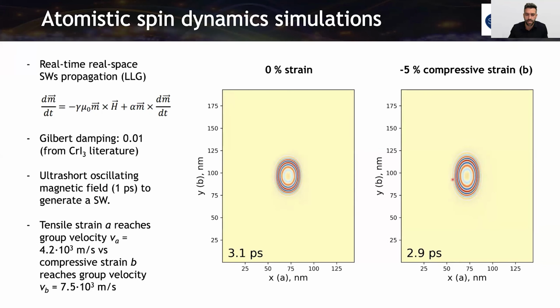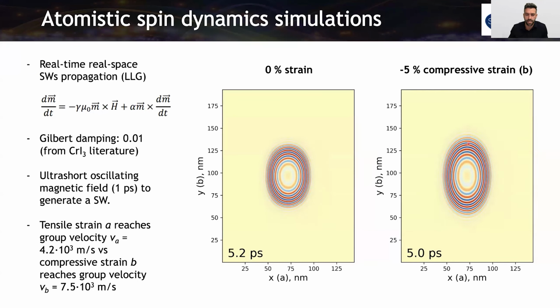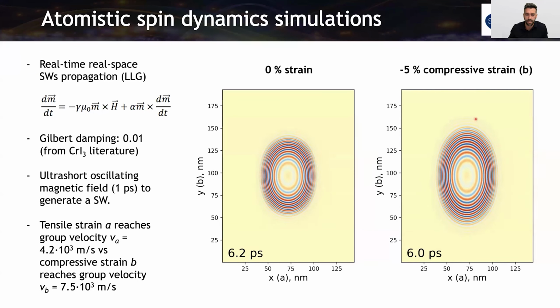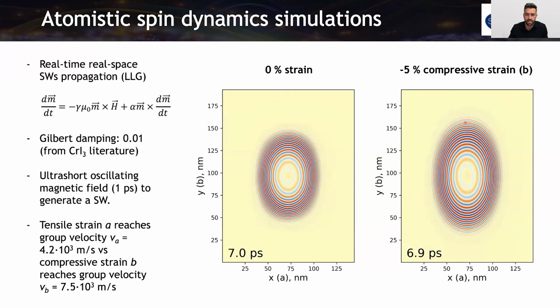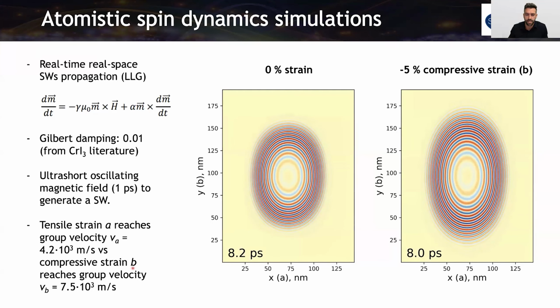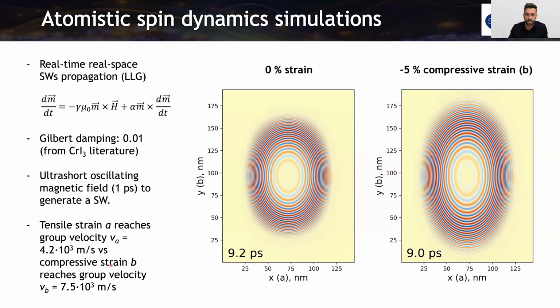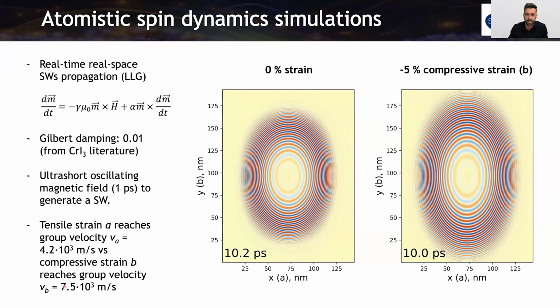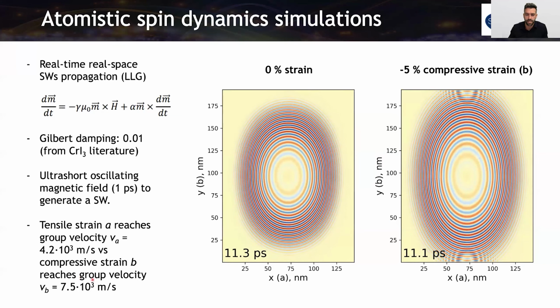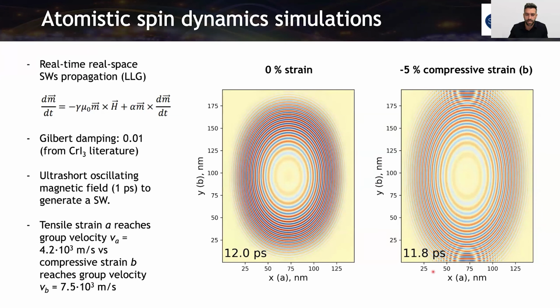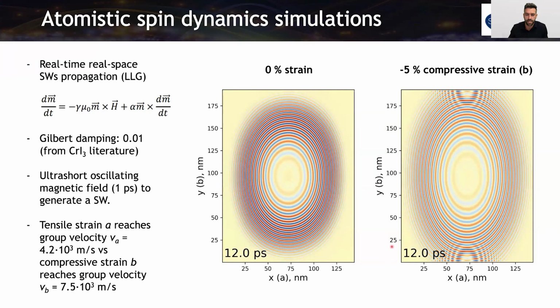And here we have compressive strain along B. And we can observe how the wave is traveling faster along this Y direction. This is following the B-axis of the material. So according to these calculations, we can achieve group velocities of 7.5 kilometers per second with this applied 5% strain on the B. So it's a way of controlling the spin wave velocity.